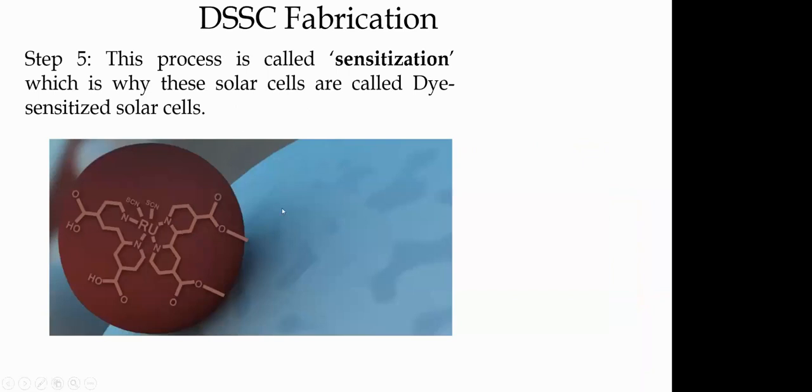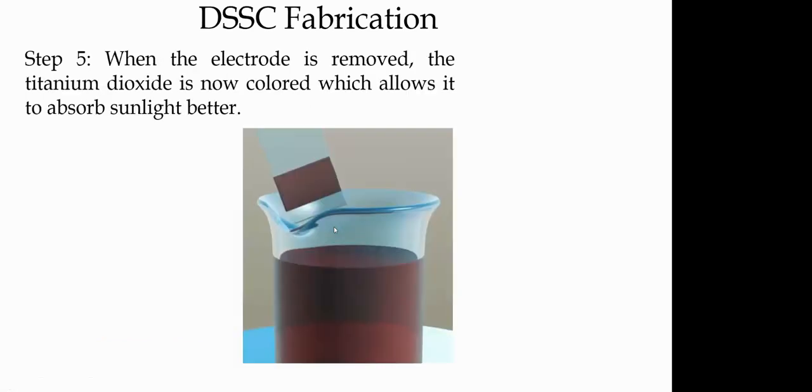So that is one dye molecule. This is physically attached to the nanoparticle of electron transport material. So any electron generated using solar energy, the excited electron, because of its higher conduction band energy, naturally drives in a few picoseconds, a very small time scale, into the conduction band of this bigger TiO2 nanoparticle, which is acting as the electron transport material, right?